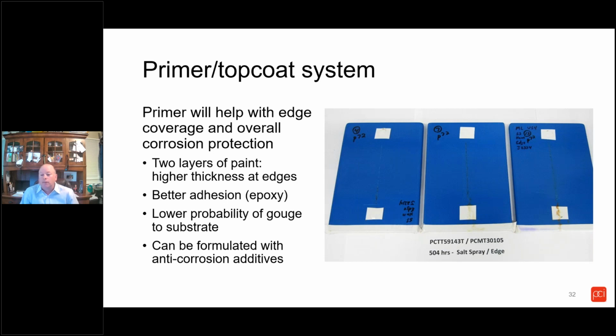If you use an epoxy primer, because of its cross-linking properties and wetting properties, you'll get better adhesion to the substrate, which helps minimize corrosion getting underneath the coating and causing delamination. Also, just by having more coating on the part, the probability of gouging down to the substrate is decreased.